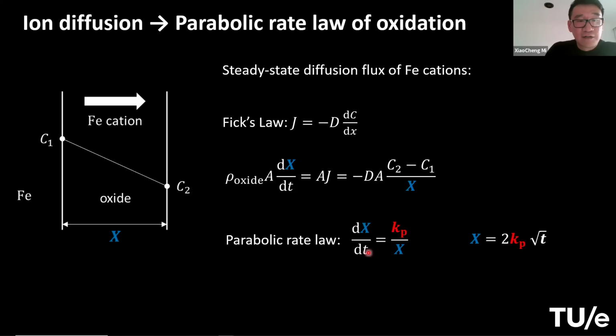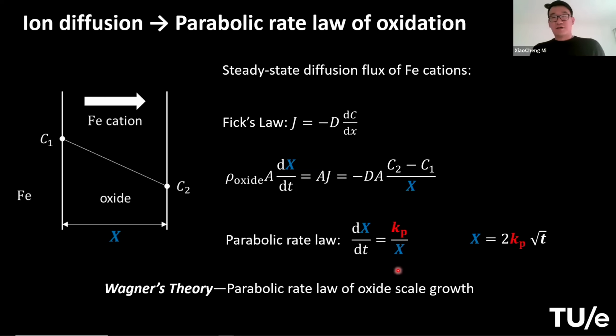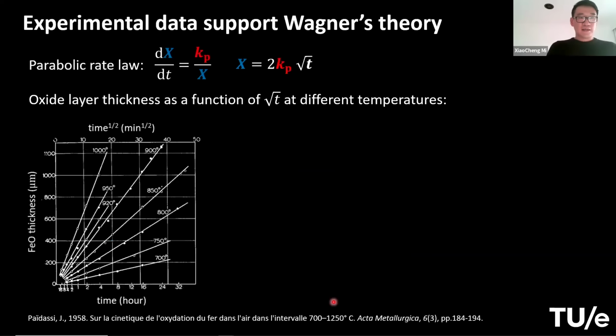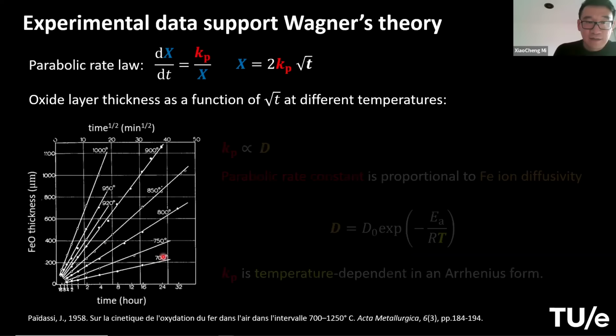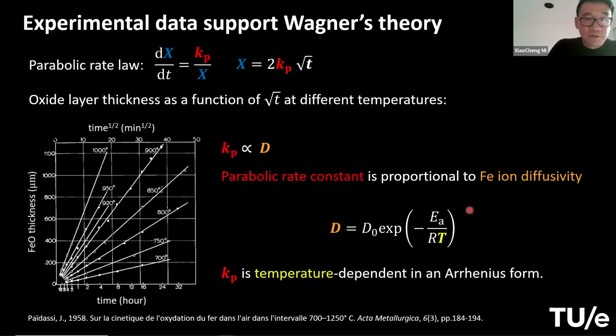The derivative of oxide layer thickness with respect to time equals some parabolic rate law constant Kp divided by the thickness of the oxide layer. And this Kp is based on the diffusivity of the ion across this oxide layer. This is known as Wagner's theory, which gives rise to the parabolic rate law of oxide layer growth. Kp can be measured by fitting straight lines to the oxide layer growth over time at different temperatures. And it follows an Arrhenius form, which has an activation energy and a pre-exponential factor, similar to gas phase reaction kinetics, because this is an activated process.